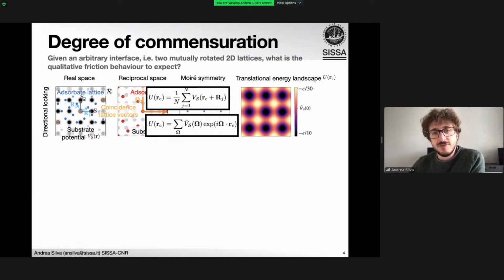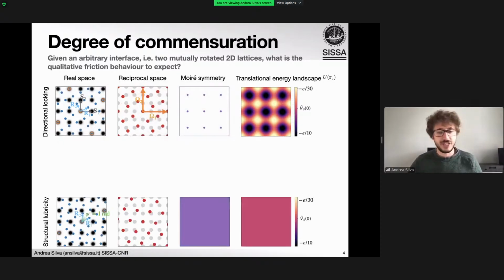On the other hand, we would have structural lubricity, where the system can slide freely in any direction. So the energy landscape that we see here is flat. This means that the two lattices are incommensurate, but there could still be, mathematically, a coincidence lattice vector in real space, but if there are none in the reciprocal one, then you would expect to see this sort of flat energy landscape.